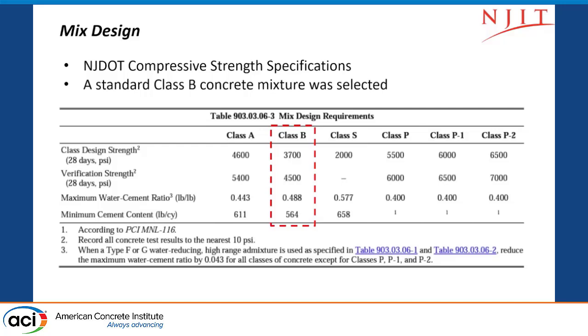So we went to the New Jersey Department of Transportation, and we focused on Class B, which is the main class used in concrete buildings. Class B has a design strength of 3,700 psi at 28 days, and New Jersey DOT has something called verification strength. To get that design, they said we need to break the cylinders at a higher PSI to make sure we are on the safe side, because there are lots of uncertainties when you break the cylinder and put the concrete in reality in the structure itself. So there is a verification strength, which is a little bit higher than the design strength, and a maximum water cement ratio of 0.488, and a minimum cement content of 564 pounds per cubic yard.